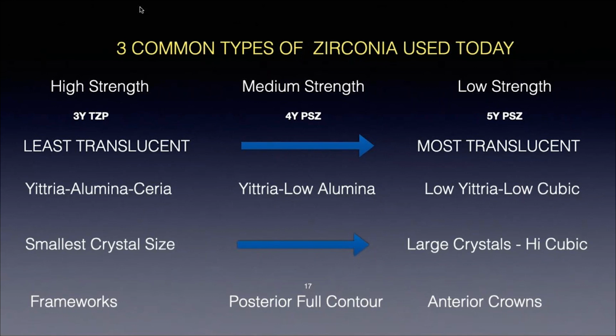The medium strength, what I would call medium strength, the 4Y zirconia, that's really all they did, was lower a little bit of the alumina content. Glidewell, I think, was the first one to do it with the BruxZir. And then you can use those on pretty much anything.